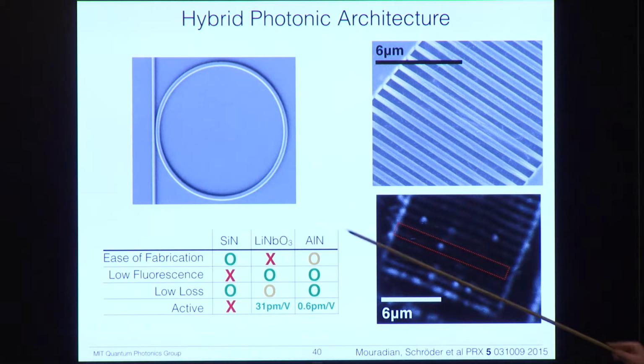So we have the platform in silicon nitride, and we have these arrays of waveguides, diamond waveguides, some with NV centers. And so this is a scanning electron micrograph, and this is a confocal microscopy image of the same array, or a similar array, where we're scanning a green laser across and collecting fluorescence. So all these bright spots are NV centers. And you can see already that the yield of the nodes is very low, so there's only a few here that we could even think about using for quantum information.